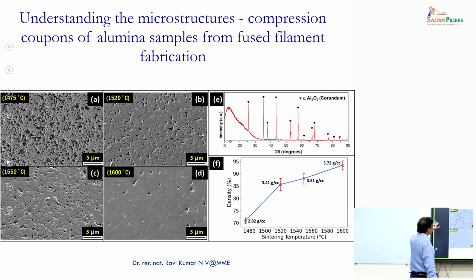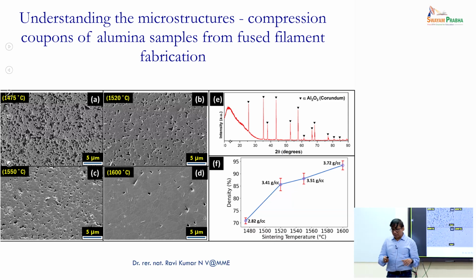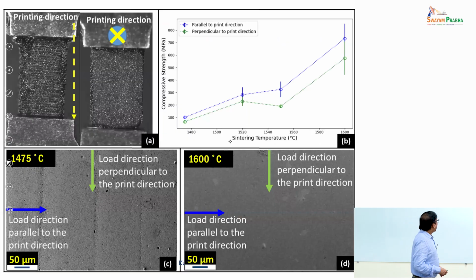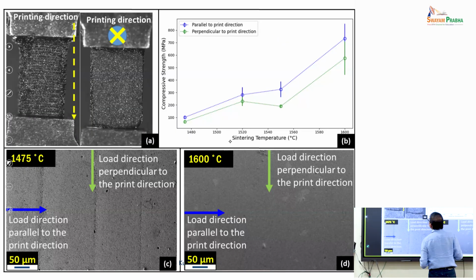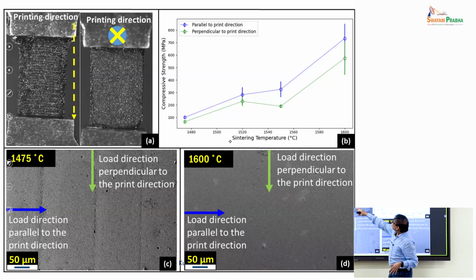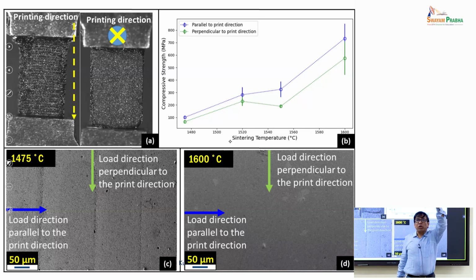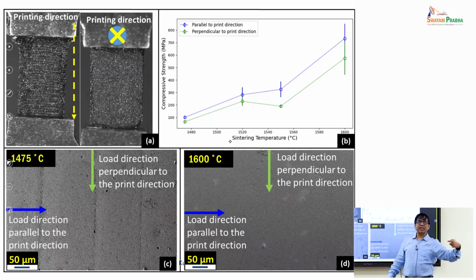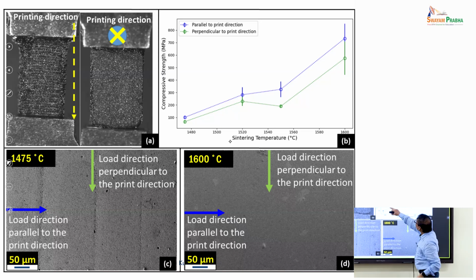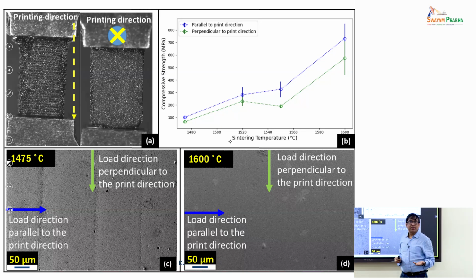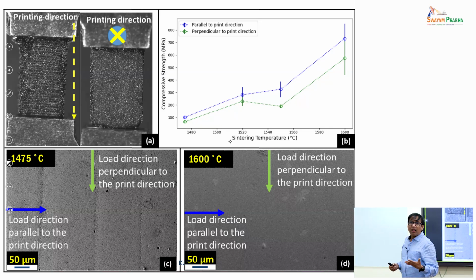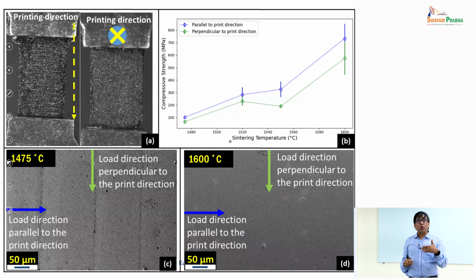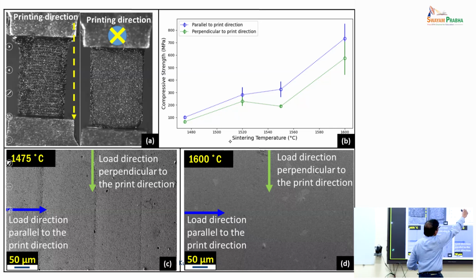And you can see that with sintering temperature, the density goes up, which is not a new thing in ceramics, but that will definitely contribute. And this is very interesting because we have now done mechanical testing both along the printing direction as well as perpendicular to the printing direction. We have plotted the compression strength, and you see a difference, so it's not the same. So long as the anisotropy is limited, you may get more or less the same result irrespective of the direction you test. But you can see even the standard deviation is not well within the error.